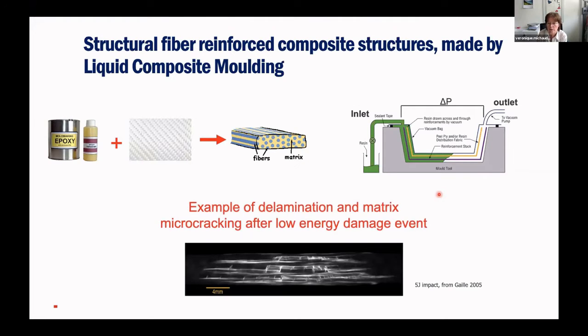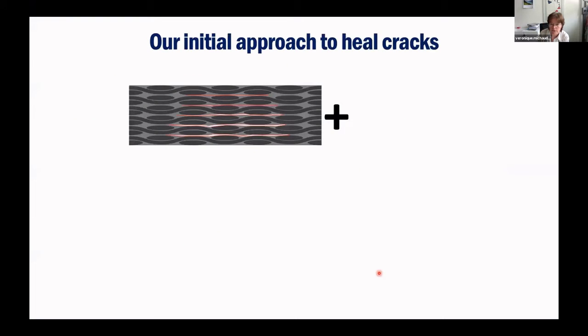And this is just an example of the type of things that we were after, an example of delamination and micro cracking after a low energy damage event. This was done by some colleague a long time ago, but I like this picture because you really see that there's a network of micro cracks that was caused in the material. You barely see it actually from the outside, which is also one of the issues with carbon composites. They tend to delaminate easily, but we don't always know it. And so we are looking after these.